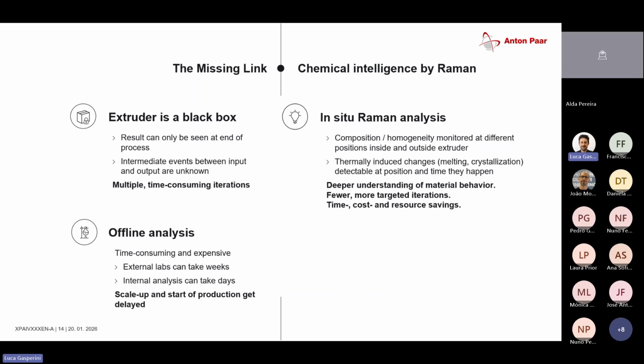295. Okay, so typically the Raman immersion probe has a maximum limit of like 275 degrees. So I think you can push to 300. This would be possible. We would need to test it, but we have not tried this in a reactor yet. What we also do is put the Raman probe into our synthesis microwaves, so we can get an idea of the chemical process. But we have to try that, obviously.